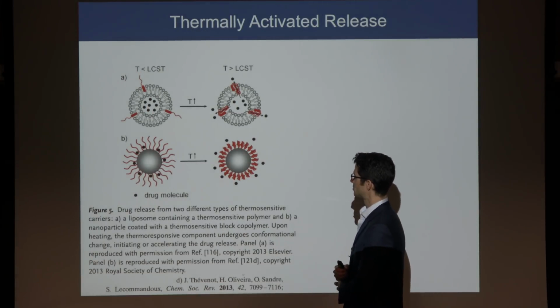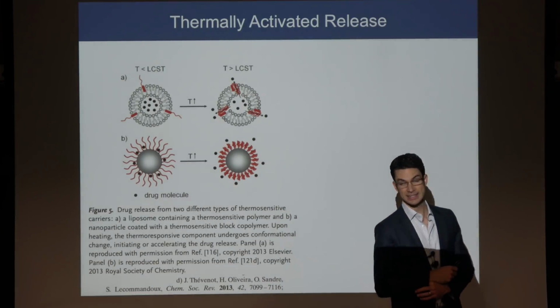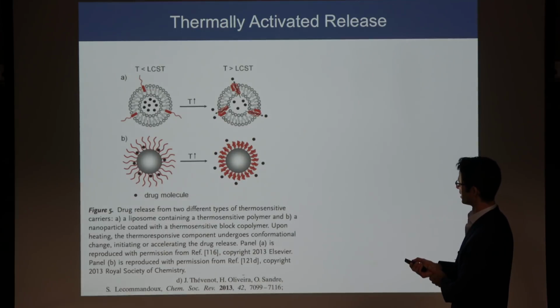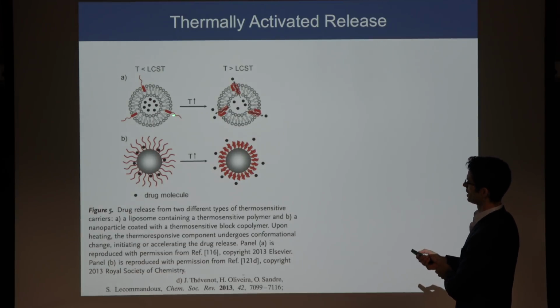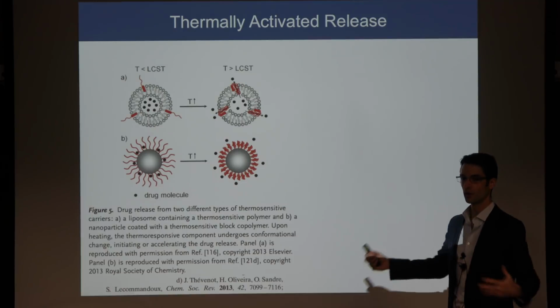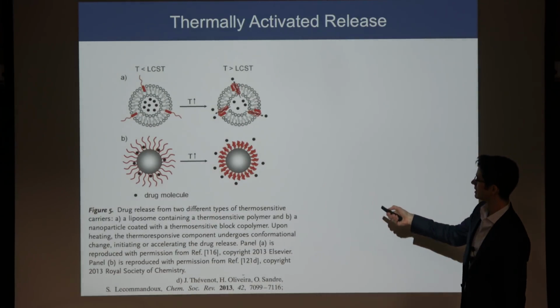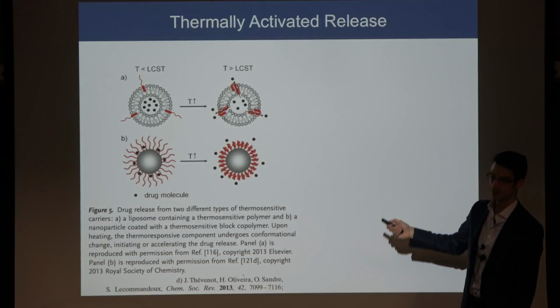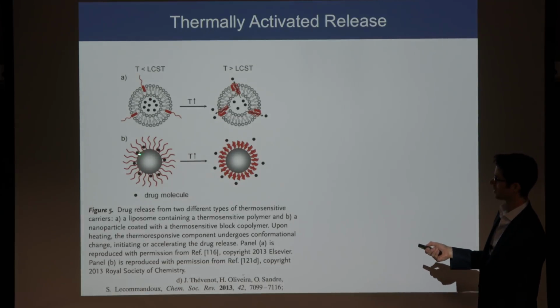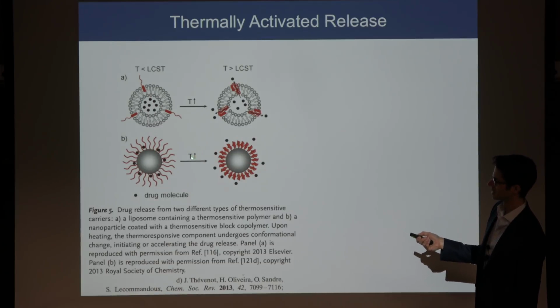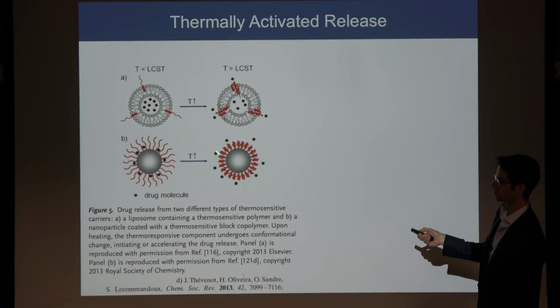This is a technique that's pretty cool for me as a polymer scientist, or polymer engineer, I guess I am both, whatever. When the temperature is below something called the lower critical solution temperature, these polymer chains extend out. And if the temperature rises above this point called the LCST, which sounds like a law school admission test, the polymer chain balls up. It goes from a coil to a globule, and as it becomes a globule, it behaves like a wedge in this bilayer vesicle and allows the drugs to escape. And you could do this with a solid particle that has these chains grafted to it. So the drugs are hydrophobic in this case, and they live in kind of the hair, just like head lice. And then you increase the temperature, the polymer chains ball up, and then there's no more room for the drug molecules, so they leave.